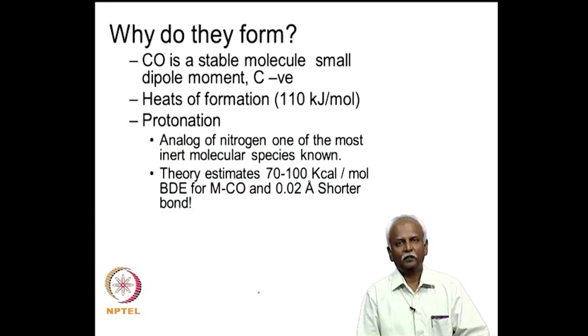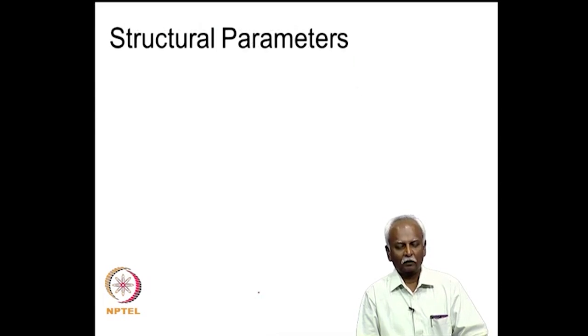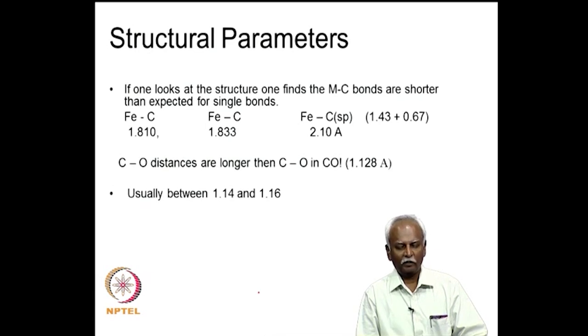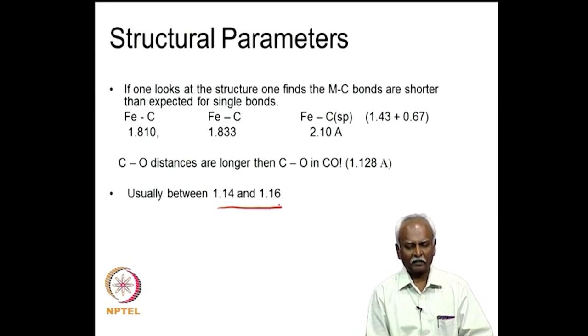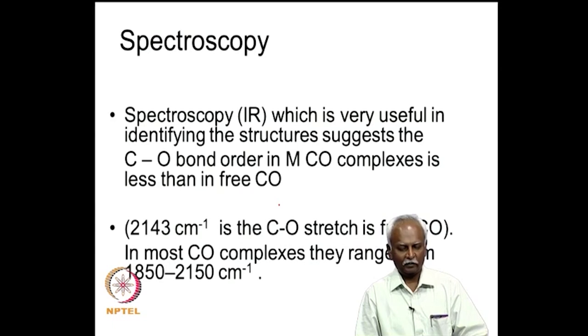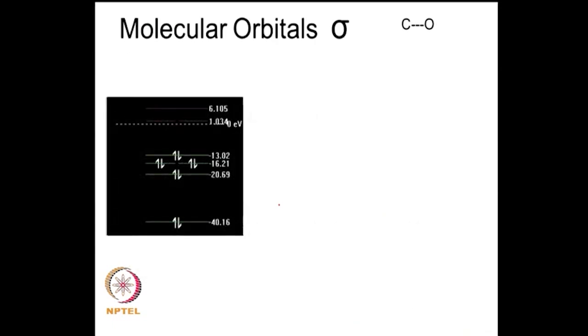That being the case, why is it that they form such stable compounds? In fact, theory estimates that the bond dissociation energy of metal carbonyls can be as high as 70 to 100 kilocalories per mole, and the carbon-oxygen bond and the metal-carbon bond are significantly different from what you would expect. So, all these things have to be explained. Let's take a look again at the structural parameters. We have already mentioned that based on the iron-carbon bond distance, you expect a distance of 2.10, and what you get is a much shorter bond distance. The carbon-oxygen distance is in fact elongated. It's usually between 1.14 and 1.16, and you have a spectroscopic feature which suggests that this frequency decreases. So, all these things have to be explained.